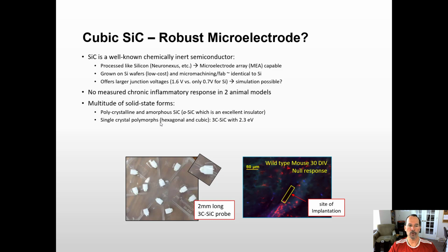There's also single crystalline forms, just like you have silicon crystals and wafers. We have this for silicon carbide. There are hexagonal and cubic forms, which are the most popular, with the cubic silicon carbide form having nearly double the band gap of silicon. So it's quite interesting that we can have access to this material, and it's extremely good in terms of its properties. So we can fashion a device where we basically have the support, the shank, made of single crystalline silicon carbide, so it's able to pierce the brain dura, and it's able to support heavily doped semi-metallic conducting silicon carbide as the conductor to replace the metal, and the robust amorphous silicon carbide to replace the polymers and plastic coatings. So we have a single monolithic system if we do it this way.